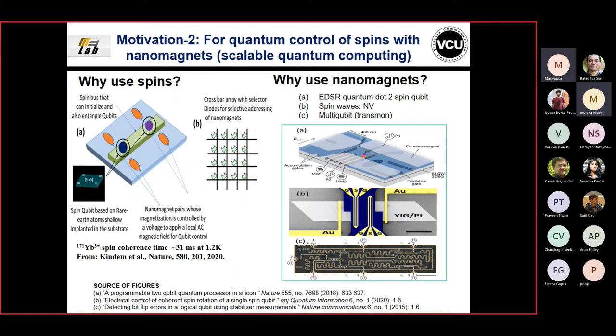Regarding single versus multiple spins: in practice you could use a single spin for a qubit, but readout could be hard since you'd need to sense its magnetic state. We have ideas where you have isolated spins - an ensemble of 50 - enhancing your readout. We also have ideas to exchange couple them and explore that direction. The energy cost for one spin versus multiple spins isn't really significantly different because the energy cost is only rotating the magnetization in the nanomagnet. If you have five-by-five spins, the only concern is if there's a gradient in the AC field, you will start dephasing.